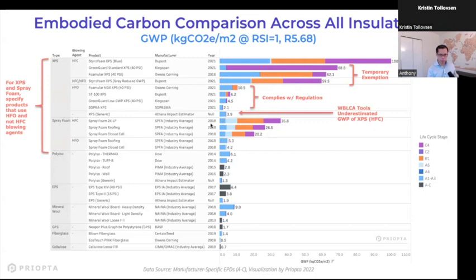And for example, Athena, which was one of the software tools that I mentioned earlier, always basically estimated XPS insulation at 3.9. So back then, 3.9 versus 100, that's a big underestimation of the scale of emissions here. But thankfully now, within the new batch of insulation products, there are still discrepancies between the different types of insulation, but they're much, much lower.